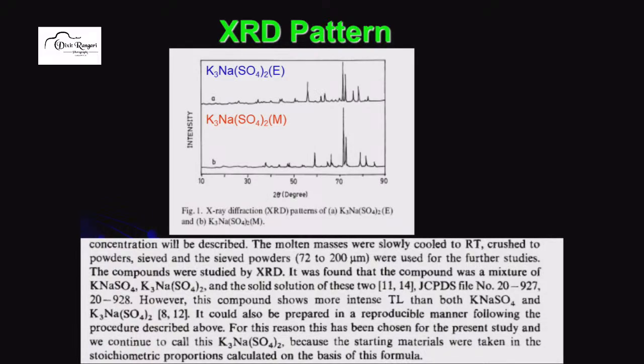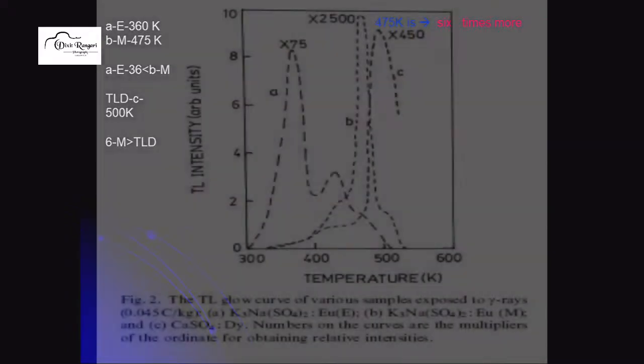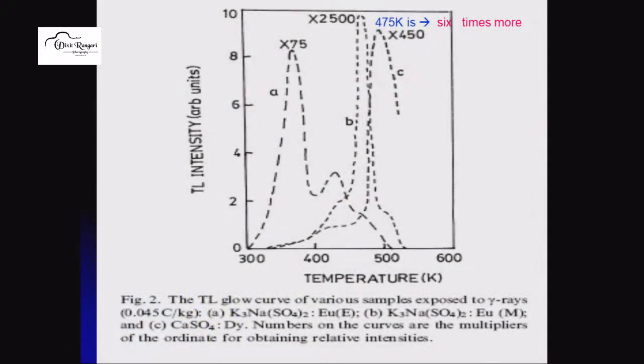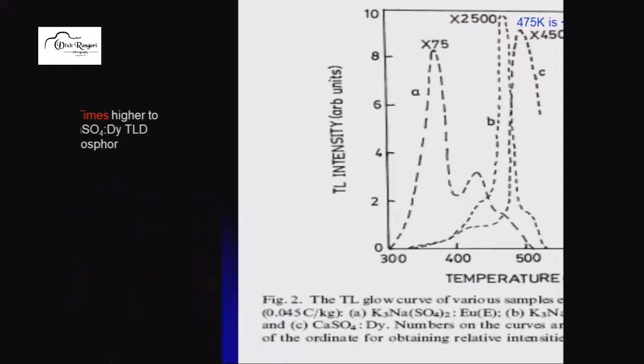The XRD pattern of the evaporation material is well matched, but in the melt method it is a two-phase material, and this two-phase material is more sensitive to gamma radiation. This was repeated a number of times, and then it is confirmed for this particular two-phase material. The peak position is simple, and the intensity is 6 times higher than the standard material, which is prepared by the Bhabha Atomic Research Center. So university people also try to prepare good material as compared to the national laboratory, by our students.